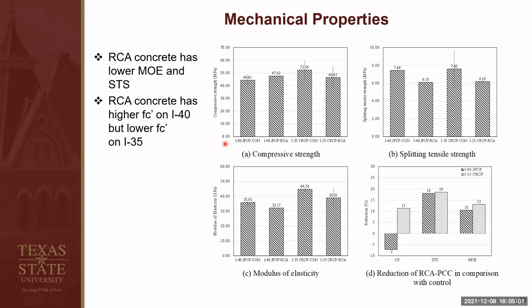We also did mechanical properties using the cores we obtained in the fields. The major conclusion is that RCA concrete has lower modulus of elasticity and split tensile strength. But we did find something very interesting: for the I-40, RCA concrete had higher compressive strength than control specimen. But for the I-35, the RCA section had a lower compressive strength compared to its control specimen.